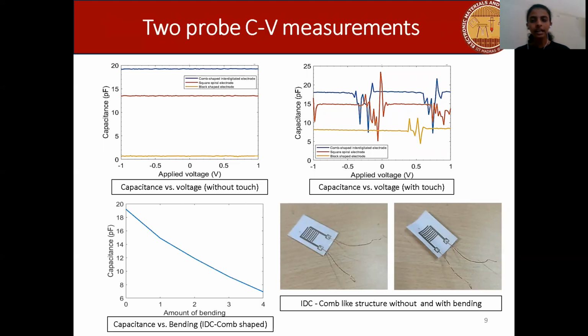Now, finally, I have observed how the capacitance is varying with bending for an IDC comb-shaped structure. In this case, I have observed an opposite trend of decreasing capacitance with the increase in amount of bending. I am still trying to figure out what can be the possible reasons for this difference, but one of the reasons can be that with varying thickness of the substrate and encapsulant, the tensile and compressive forces can get reversed, because of which we can observe a total reversal, that is a negative trend in the variation of capacitance, which is in contrast with the simulation results.